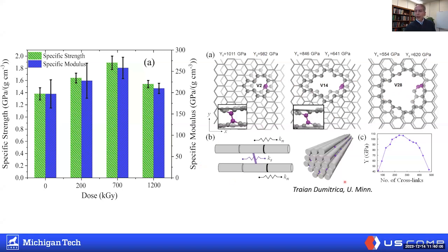Also, we could take a look at how these crosslinks you see in purple affect a carbon nanotube bundle. So it's not just what happens between two parallel sheets, but what happens with the bundle in the lower image. In computational simulation, looking at modulus, we can show that there is indeed a sweet spot where if you create the right number of crosslinks, you can maximize the modulus. If you make too many crosslinks, you start to degrade the material.